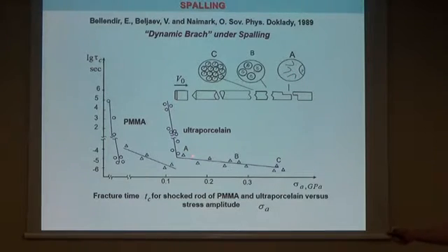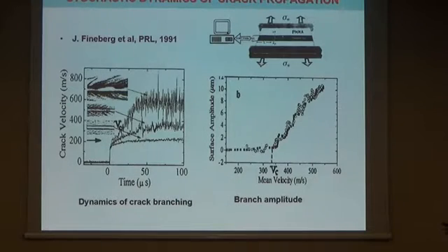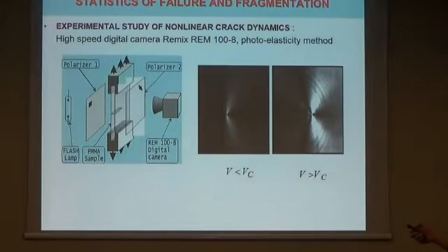With this, practically a parallel branch appears in the variables of characteristic time of failure and values of stress amplitude, which reflects very pronounced similarity. It means the damage-failure scenario doesn't depend on stress. It's a consequence exactly of resonance excitation of these zones, which have the nature of blow-up solution. And these data were used to explain experimental data by J. Fineberg concerning stochastic dynamics of crack propagation.